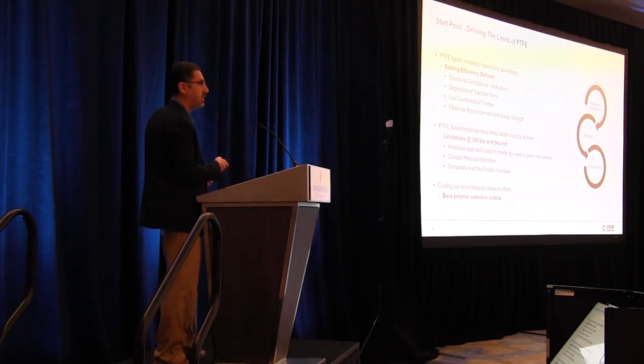So first of all, it has an excellent elastic response, so when you apply a load on PTFE, it will try to respond back, bounce back, so that creates a wonderful sealing restoring force. It can be used as a seal grade efficiently. Then it has excellent tribological properties as well. So during the rubbing action, PTFE lays a transfer film on the counter surface, so generates a PTFE on PTFE contact, which has one of the lowest coefficients of friction of all the materials available to us in a practical manner. So very good friction and wear material. It is not a very stiff or a strong material inherently, but by utilizing very common fillers like carbon or glass, it can be made stiff and strong and creep resistant.